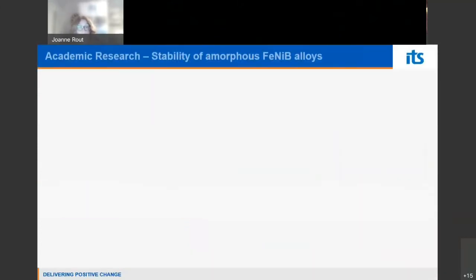Why would we do this? Well, the reason we were interested in these materials, and there was a hint on the cover of the New Scientist magazine, is that these alloys in the amorphous phase have high magnetic susceptibility, low coercivity, and high electrical resistance. And why are those properties interesting? This means that when these materials are used for a transformer, the eddy currents are much lower, which means there are fewer losses. When you have a transformer, you subject it to alternating magnetic fields, and currents are induced. If you can prevent those currents, then it doesn't heat up as much and you don't have as many losses.